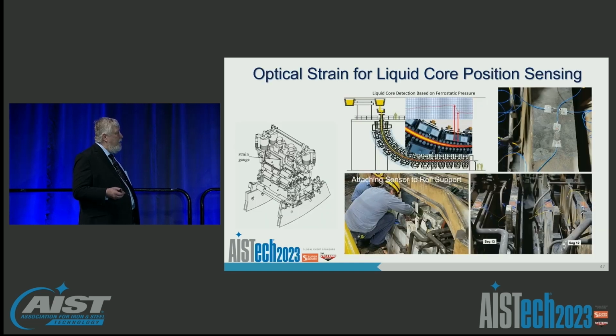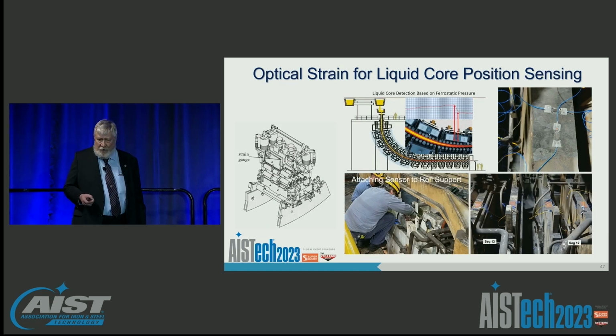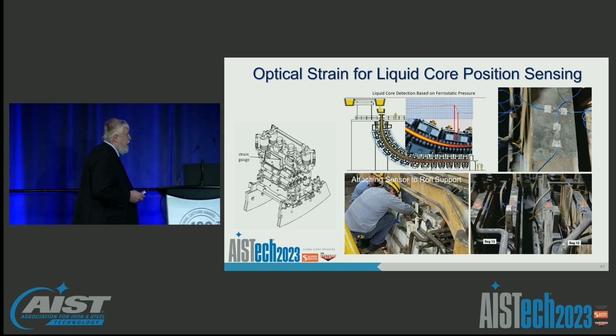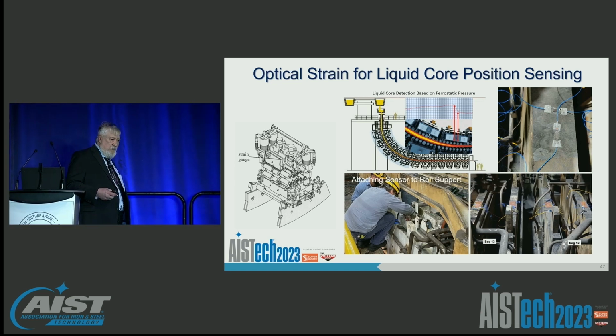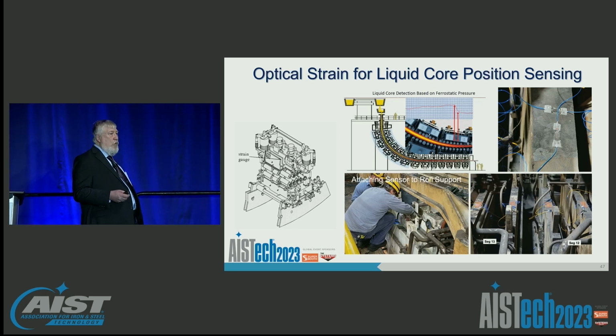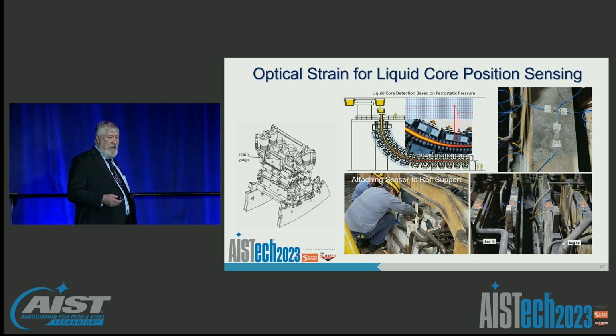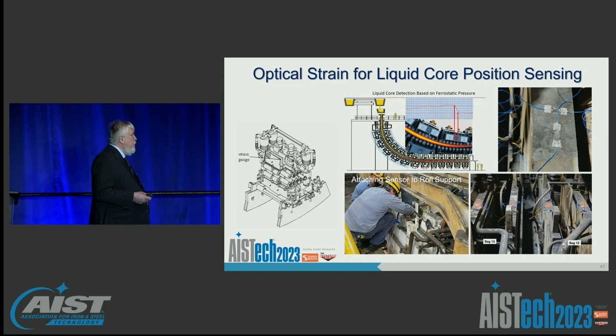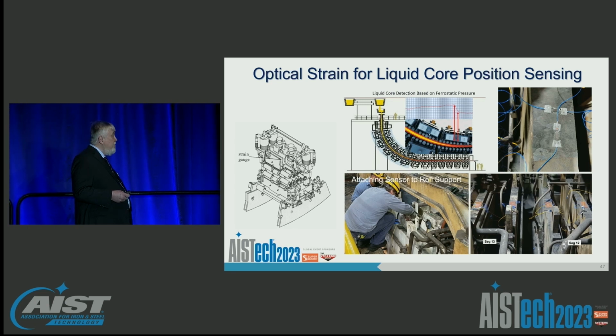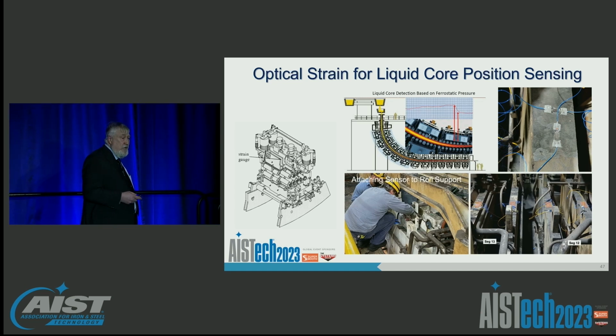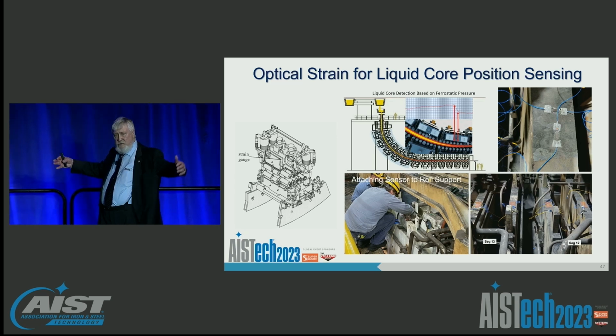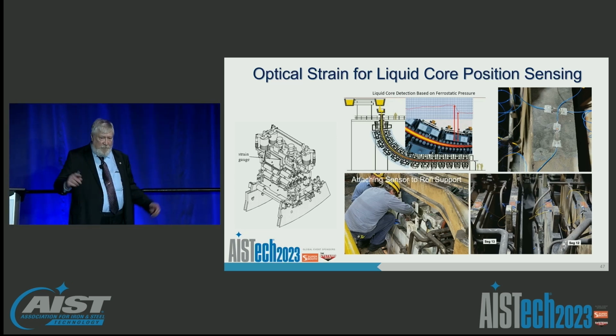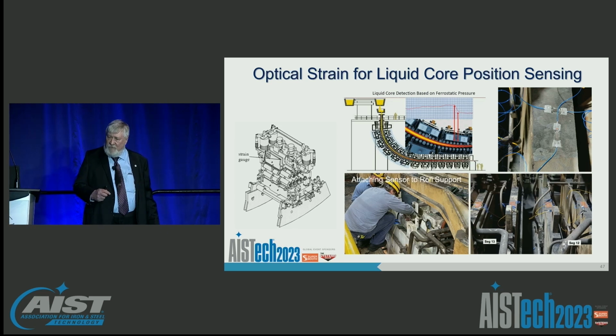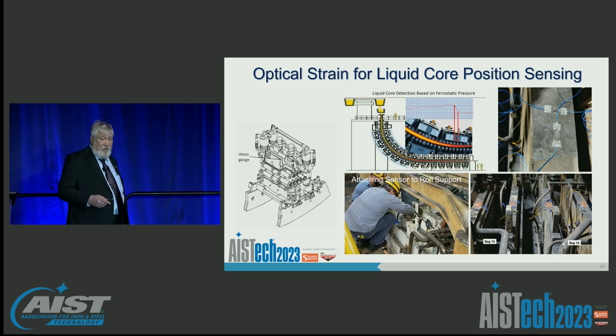We've also taken fiber optic sensors and we've applied them in the real world, and we've put them on continuous casting support beam structures to do essentially roll force measurements to detect the presence and absence of liquid core position. And the beauty of using fiber optics over conventional sensors in this environment is that these sensors can be multiplexed. They can be daisy-chained. And so we can have one fiber feeding a large number of sensors and instrument a whole segment or a bank of segments with one fiber, as opposed to having power run to doing strain gauge measurements at each location.